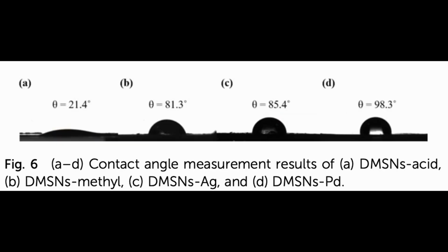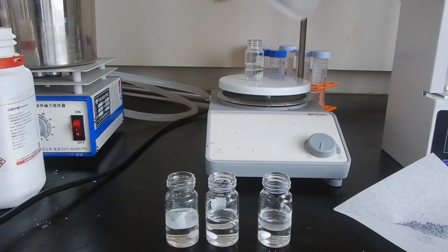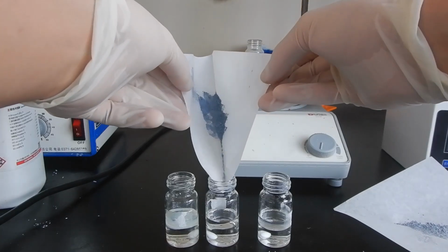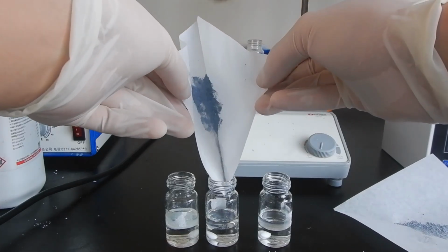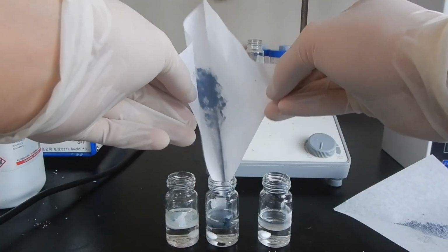Finally, the contact angle measurement, as shown earlier, measures the hydrophilicity of DMSN's surface by adding a drop of water to it under high-speed camera, highlighting the effectiveness of the hydrophobic surface treatment. All of these characterization results tell us that our nanoparticle synthesis worked nicely and its properties aligned with literature.